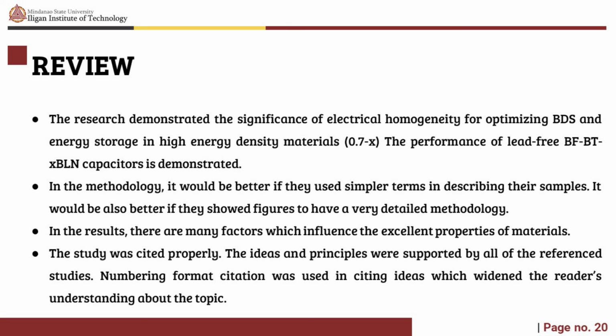The MLCC multilayers were sintered at 890 degrees Celsius for 2 hours with an intermediate binder burnout step. The densities of sintered ceramics were obtained by the Archimedes method and achieved more than 95% of the theoretical density. The researchers assume that numerous factors contribute to the excellent properties of these materials. The high value of WREC is a direct result of being able to apply a significant electric field without causing the breakdown of a material whose crystal chemistry is defined to accommodate highly polarizable ions inside a matrix of different sized ABO3 perovskite unit cells.